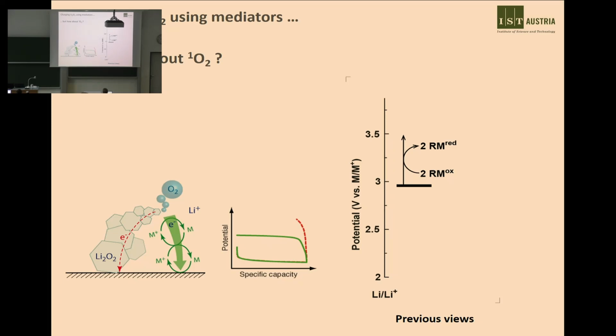So what's the relation to the singlet oxygen here? One may come up with a threshold for a 2-electron oxidation. We know we have a 1 electron volt difference between singlet and triplet. So if it's a direct 2-electron oxidation, we would divide this by 2, and we would end up with a threshold around 3.5 volts.